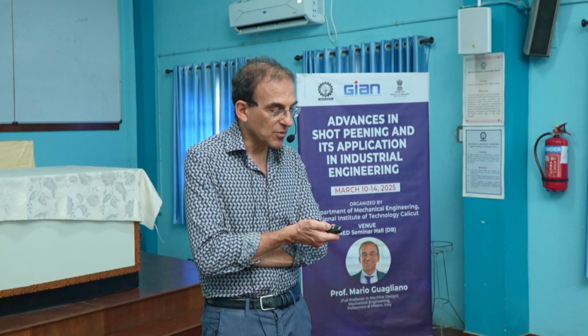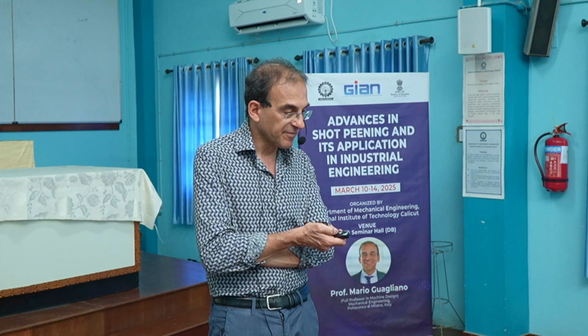FKM requires the definition of few parameters, so it's easier to use. This is for calculating the fatigue limit, and this is the main advantage of the FKM. The nominal stress approach categorizes the different notch effects, and the notches we used were among the ones considered by the nominal stress approach in FKM; otherwise we had to calculate by means of a finite element code. For the theory of critical distance, we used the Sines criterion because, even if the load is uniaxial, shot peening induces a biaxial residual stress state. So for a final estimation of the effect of residual stresses, we had to use this multi-axial fatigue criterion. Okay.